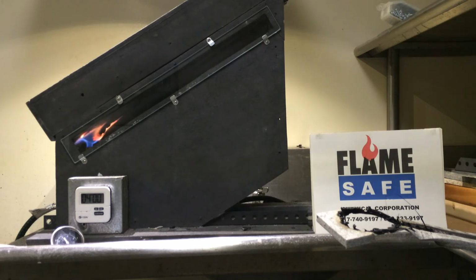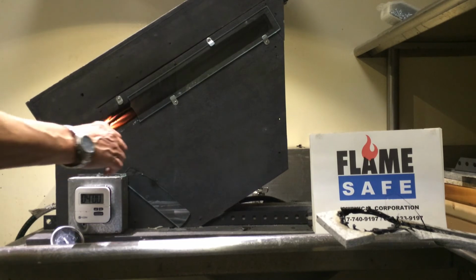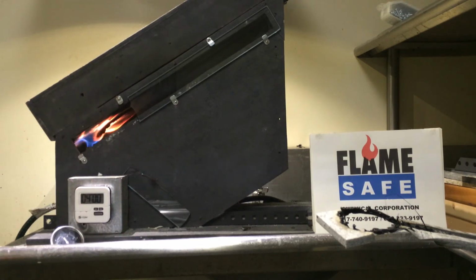Ordinarily, this test, as I mentioned, takes 4 minutes. We're going to run this test for an additional 1 or 2 minutes to show the effectiveness of the coating. The heat is so intense that it shattered the glass, if you'll notice. Happens sometimes.